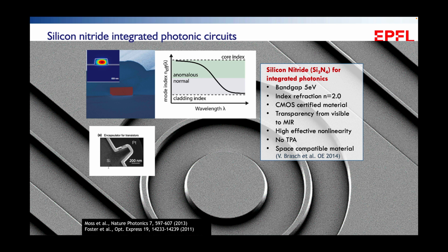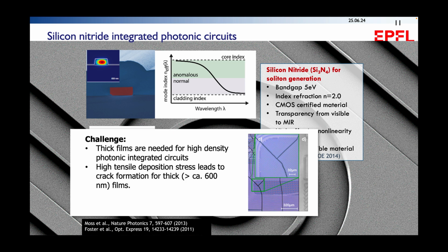Now, in terms of optical properties, there are a few very notable ones. You have a high effective nonlinearity and a bandgap of 5 eV, so you can operate into the visible. The material is also CMOS compatible and can be simply deposited by chemical vapor deposition. So how can we create really low loss waveguides from this material? What we have overcome is one of the key challenges in this material, which is crack formation. If you grow a few hundred nanometers of these films to confine light, cracks form due to the very high stress in the material.